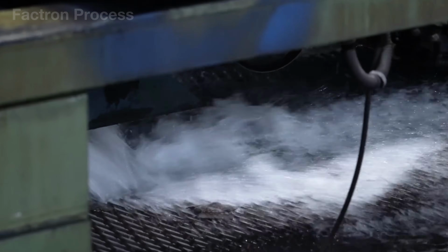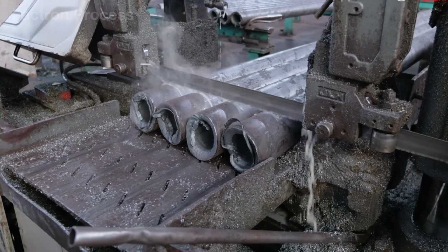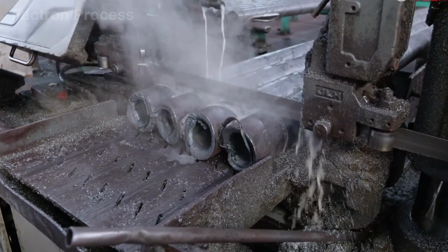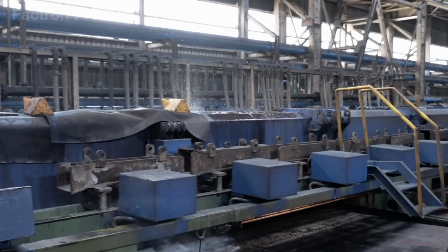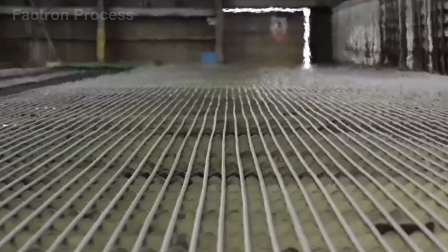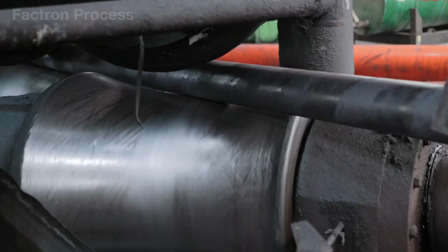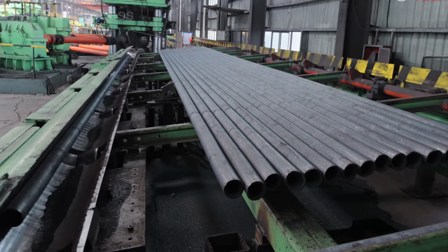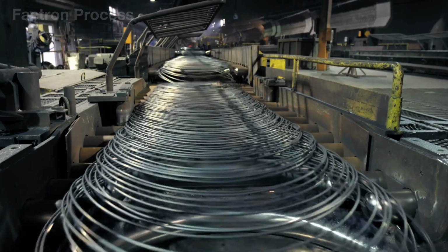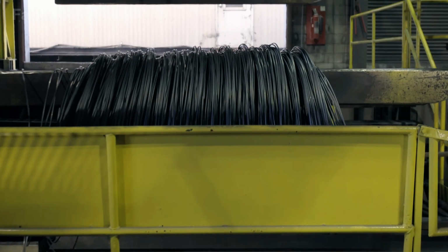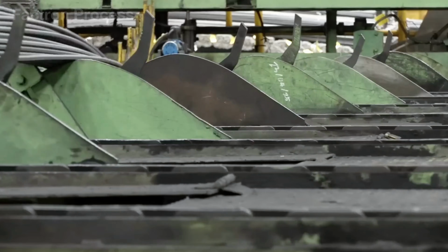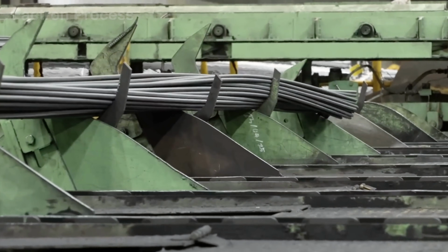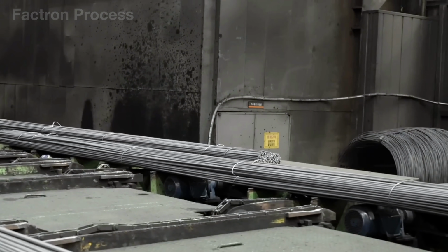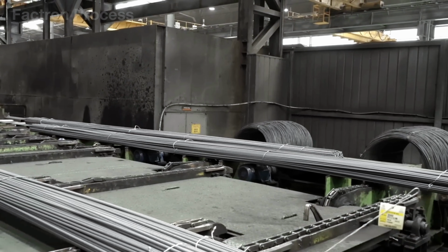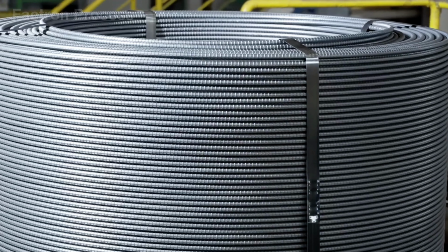by high-pressure spray systems that create a dense white mist. This rapidly but evenly lowers the temperature to prevent cracking, while powerful industrial fans blast air across the steel to preserve its crystalline structure. Once the temperature has fallen, ultrasonic sensors, high-resolution cameras, and mechanical testing equipment work together to detect everything from hidden cracks to the material's tensile strength. Steel strips that pass inspection are then tightly wound into massive finished coils, stamped as approved, and transferred directly to storage, ready to serve hundreds of industries.